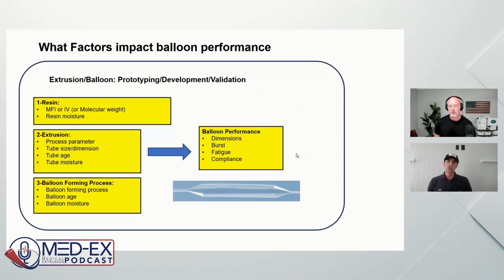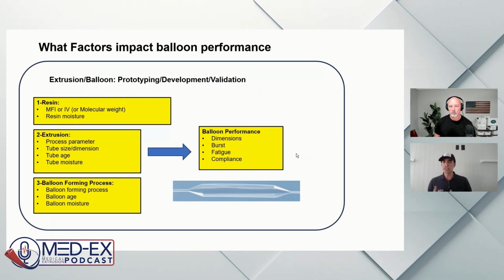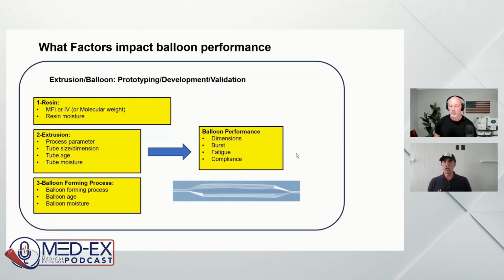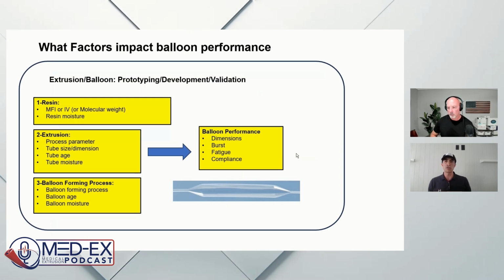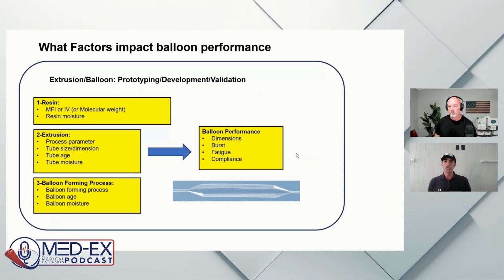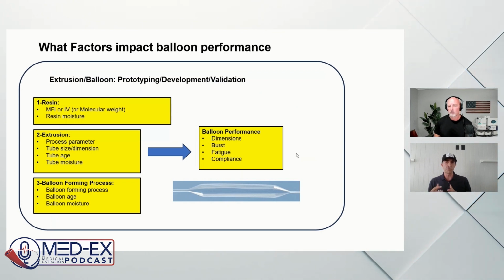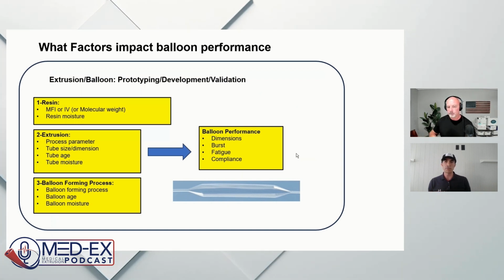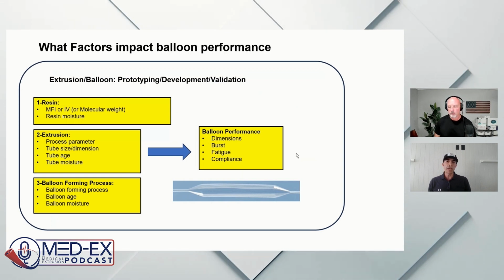On the extrusion level, you have all your process parameters, right? You have your drawdown ratio at the die, your cooling system, or puller speed. All these things would impact the crystallization of the molecules. A slower crystallization or a fast crystallization could give you different tubes that would perform differently in terms of stretchability or stiffness of the material. And of course, the tube size dimension that we already mentioned is a very important aspect of the extrusion side.